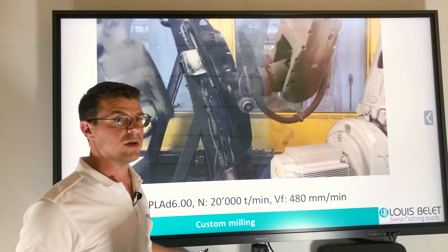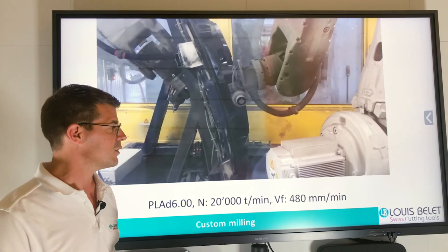One development was for the automotive industry. The part you see here is a trunk of a car. The customer uses robot arms, and on each robot arm is an end mill that we developed — a 6 mm end mill in carbide — to make openings into the trunk for fixing it to the main body or for headlamps. The cutter penetrates, drills, then contours to make the required shape. The customer runs at 20,000 RPM on the spindle with a feeding speed of 480 mm per minute.